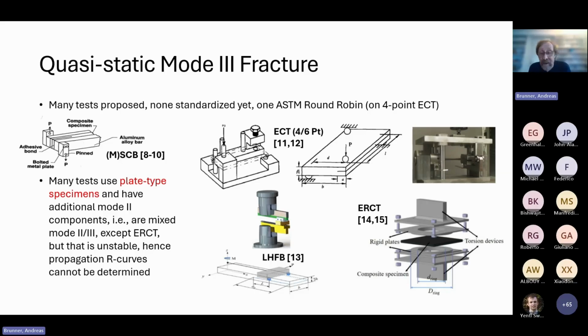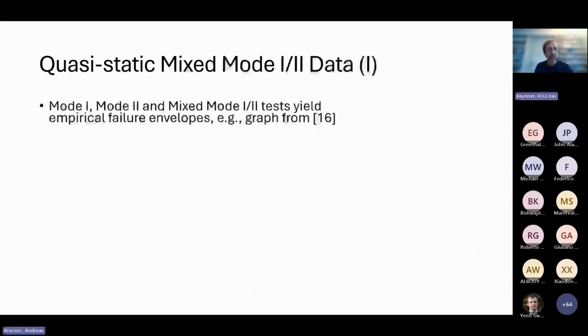However, the disadvantage of that test is it's unstable. So you can determine initiation values of mode 3 fracture toughness, but not any propagation, which of course would be required if you wanted to apply these data in structural design, because you have to understand how the delamination will grow and propagate.